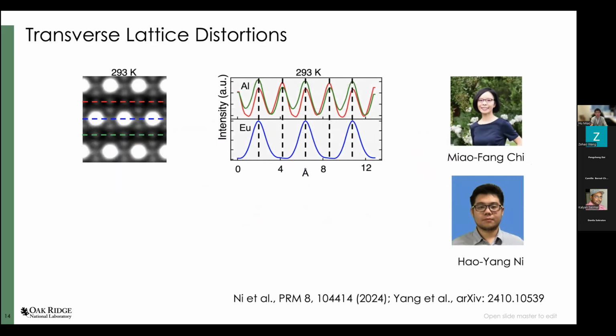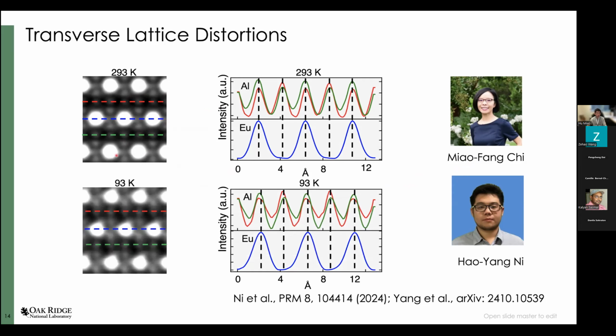We can do a bit better by imaging the lattice distortion using TEM. So Miao et al. helped us to check the image of europium aluminum 4. Here's the TEM image and TEM cut at room temperature. Once you're cooling down, you can start to see the displacement, and they can confirm the lattice displacement is coming from the aluminum atoms that is transverse, that is perpendicular to the CDW propagation wave vector.